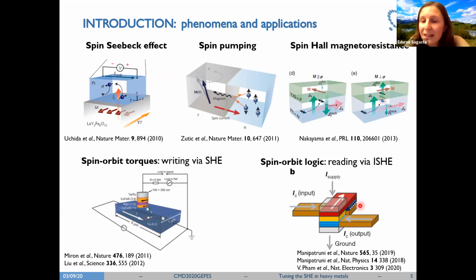In case of reading the magnetic memories, we have the case of the inverse spin Hall effect, because here we have the proposal of Intel, where they are basically injecting a current from the ferromagnetic element, which will be our memory. So here, as it is a ferromagnet, we will have a spin current flowing in the block. And due to the inverse spin Hall effect, a charge current is generated in the transverse direction that we can measure and therefore extract information of the memory element. Our group at CIC nanoGUNE has been collaborating with Intel, and we have quite recently published this paper. So I suggest that if you are interested in the topic, you can have a read.